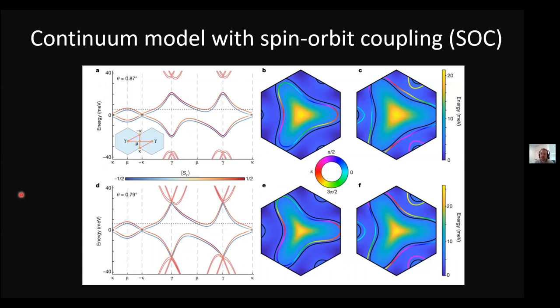So for the lattice relaxation, the best thing I can tell you at the moment is based on simulations. In order to match some of these values of the gaps, we were using continuum model simulations, and I forgot the exact numbers, but you can see in our paper the ratio of AA to AB tunneling. I think it was around 0.8, no, maybe 0.5. So 0.5. Okay. Yeah, but please verify this in the paper.